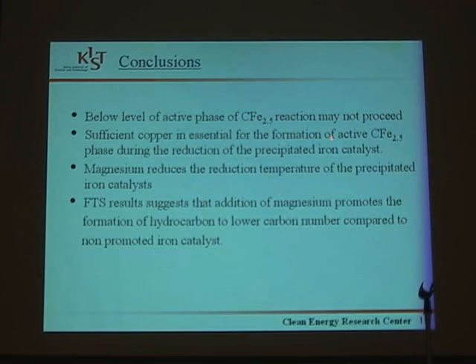Sufficient copper is essential for the formation of the active, that is carbon Fe2.5, phase during the reduction of the precipitated iron catalyst. Magnesium reduces the reduction temperature of the precipitated iron catalyst. FTS results suggest that addition of magnesium promotes the formation of hydrocarbons of lower carbon number compared to the non-promoted iron catalyst. So the next step is, since magnesium promotes the activity of the FTS catalyst towards lower carbon number hydrocarbons, we are going to standardize the amount of magnesium to Fe so that we can get the product which will be more towards the middle distillate or gasoline range.